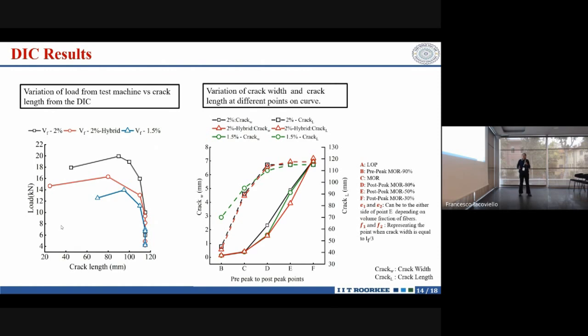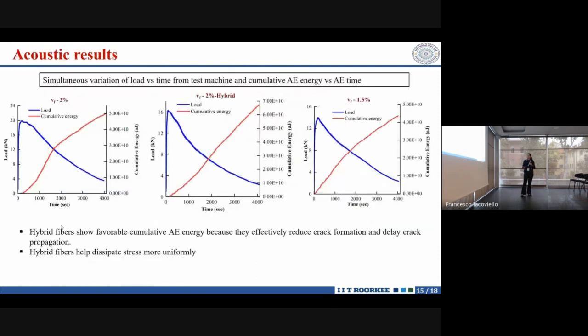So all these outcomes are visible in these results, and from the acoustic emission results this is also quite visible, like in 2%, the acoustic energy we have. This is the combined plot of the load versus time from the test machine and the cumulative energy versus time from the acoustic emission result. So acoustic energy is also showing favorable results for the hybrid, showing that hybrid fibers are engaged in overall improving the performance of the material.